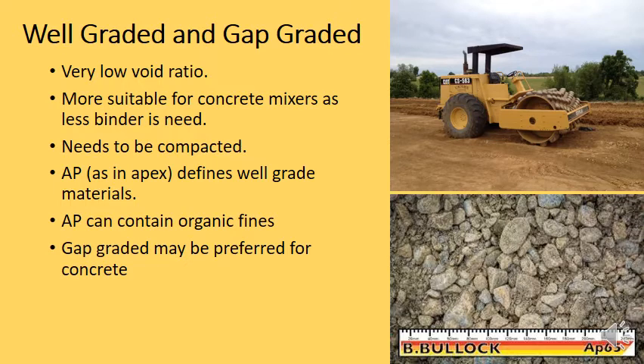And this is where we would use something like a sheep's foot roller, similar to that sheep's foot roller that you see in the top right corner. It's compacting the aggregate so that you can take out all of the air voids so it has a high compressive strength. That's why you need to do this when you're building a road. You're pressing down on the well-graded or gap-graded aggregate using a compactor in order to give it that strength. If you don't do that, then it won't be strong.